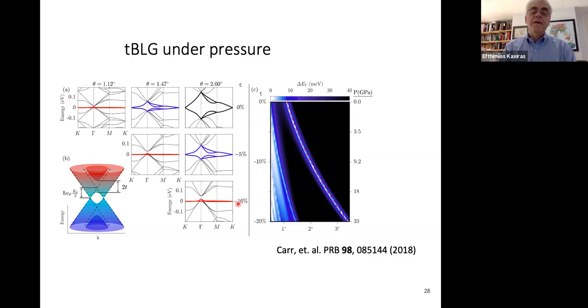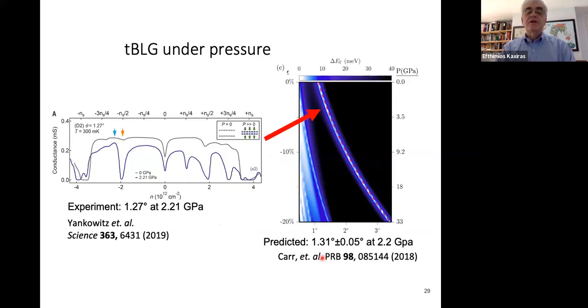And you can express this compression between the two layers as an equivalent pressure in the gigapascal range. And you can create this phase diagram of the magic angle for flat bands at any angle. So this was work that was performed by Stephen Carr. And it was verified by experiment a little bit later. So these are experiments from the group of Corey Dean and James Hone at Columbia.